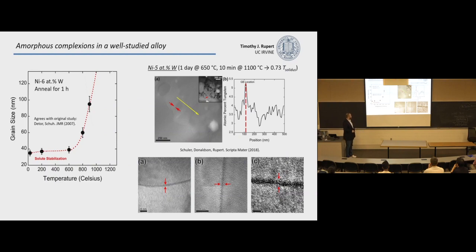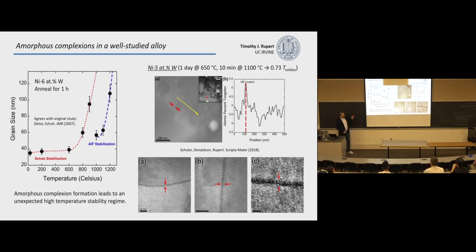amorphous grain boundaries. And the reason this matters is if you go back and add this high temperature data to this type of curve, you actually find that your grain structure is more stable at 1,000 degrees C than it is at 900, which is a very counterintuitive type of thing. You tend to think as you increase the temperature, your grain size will grow and coarsen. It's more sort of extreme type of conditions.